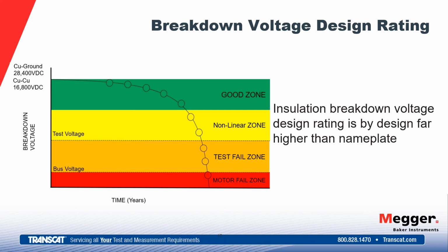The only way the insulation will be degraded is by excessive charge flowing through the weakened material, and that's not happening with a good insulation system. However, if your insulation is degraded, then the current that flows with the arc can potentially cause further carbonization of that degraded area. Since the test is well controlled and regulated, as in that slide we talked about, vintage instruments, this instrument in newer modern times has the ability to stop the test before that occurs.